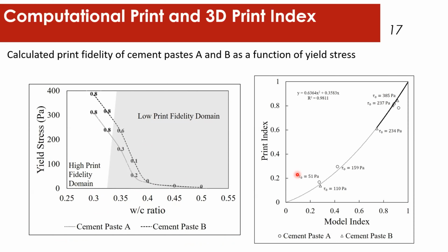Now, if I plot the model and actual print index one-on-one, I see a strong near linear relation. And if I put the yield stress on it, I see that the good printing outcome was observed at a printability index of 0.7 or greater. So this shows that at a printability index of 0.7 or greater, that is, a yield stress of greater than or equal to about 237 Pascal is required to produce good printing outcomes.